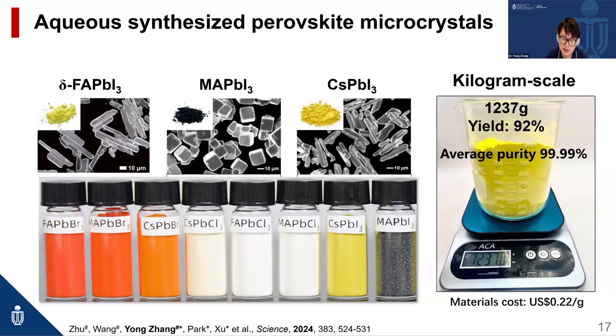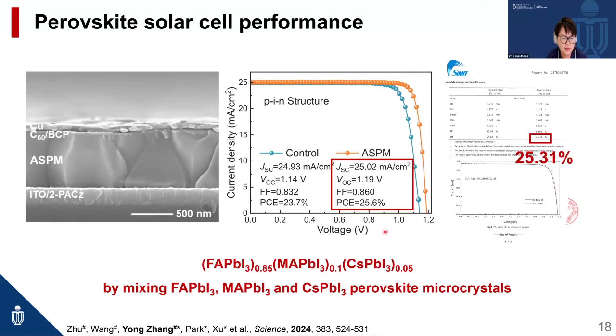Since the raw material cost is very low, we calculated the materials cost used in this reaction. We found that the price of FAPbI3 microcrystal is about $0.22 per gram. Then we used these three kinds of perovskite microcrystals as a mixture to fabricate this composition of perovskite film.